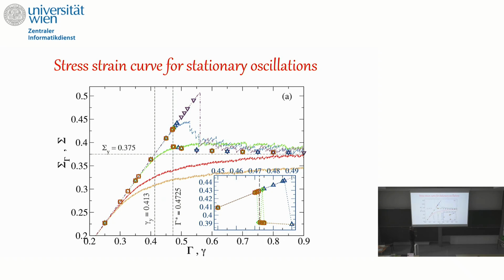And now if you start very, very fragile, like the violet case, then you fail later, you fail here. But once you fail, you reach exactly the same stationary state, which is this mixture between solid and liquid with a shear band. Okay?